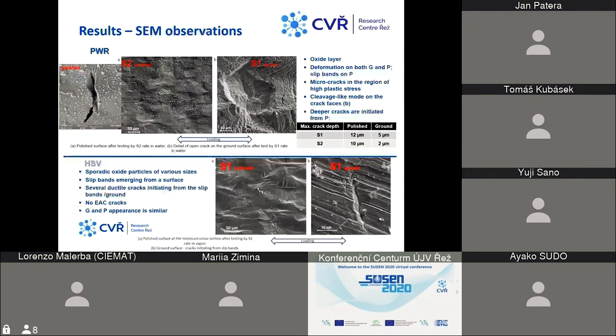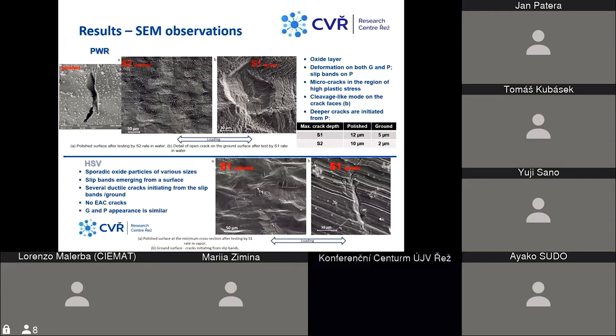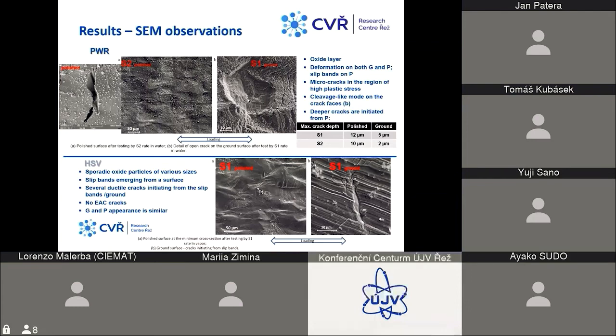We also performed the SEM observations of the PWR and hydrogenated steam vapor. We found the oxide layer in the water environment and deformation on both ground and polished sides of the sample, and slip bands were pronounced on the polished surface. The micro cracks were found in the region of high plastic stress in the narrowest part of the tapered sample, and we also found the cleavage-like mode on the crack faces on the ground side. The deeper cracks were initiated from the polished side of the sample. We also performed focused ion beam investigation to find the depths of the cracks.